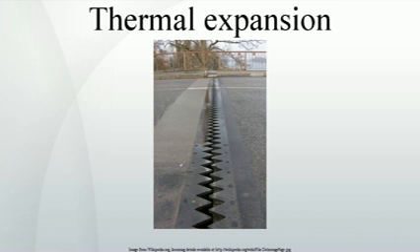At the glass transition temperature, rearrangements that occur in an amorphous material lead to characteristic discontinuities of coefficient of thermal expansion or specific heat. These discontinuities allow detection of the glass transition temperature where a supercooled liquid transforms to a glass. Absorption or desorption of water, or other solvents, can change the size of many common materials. Many organic materials change size much more due to this effect than they do to thermal expansion. Common plastics exposed to water can, in the long term, expand by many %.